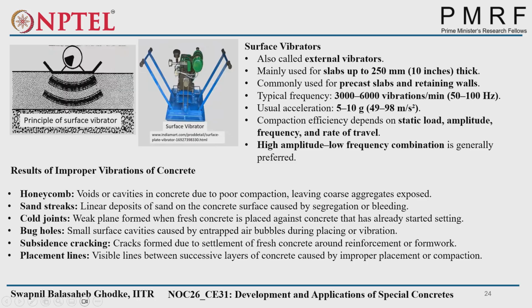Under vibration creates honeycomb, voids or cavities in the concrete due to poor compaction. Sand streaks, linear deposits of sand on the concrete surface due to bleeding, are from over vibration. Cold joints, a weak plane. We saw that cement particles will come to the surface, and if you pour a second lift into the concrete, weak bonding will result. Bug holes, small surface cavities caused by entrapped air bubbles during placing and vibration. Subsidence cracking means cracks form due to the settlement of some of the concrete around the reinforcement. Placement lines, visible lines between successive layers of concrete caused by improper placement and compaction.